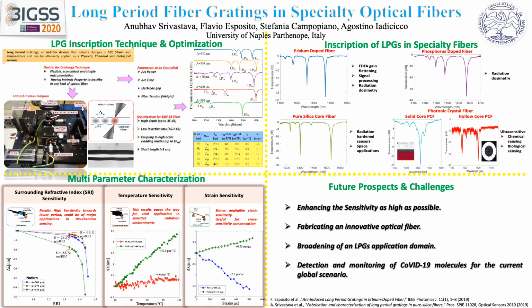So long period gratings, whose length typically lies in the range of 100 micrometer to 1 mm, are inscribed by inducing a periodic longitudinal perturbation by acting on the refractive index of silica and on waveguide geometry along the optical fiber core. There are different techniques which have been employed to inscribe LPGs, the most important being namely UV radiation, mechanical microbends, ion implantation, CO2 lasers, IR femtosecond lasers, and electrical arc discharge.